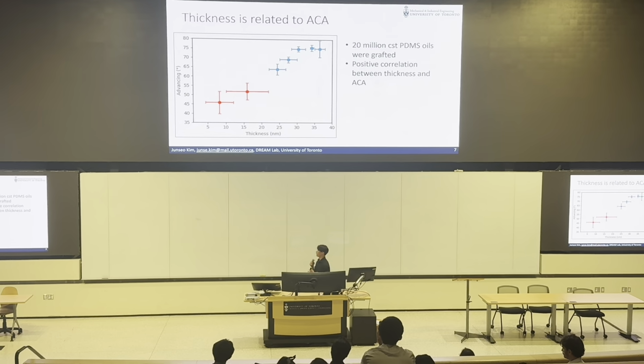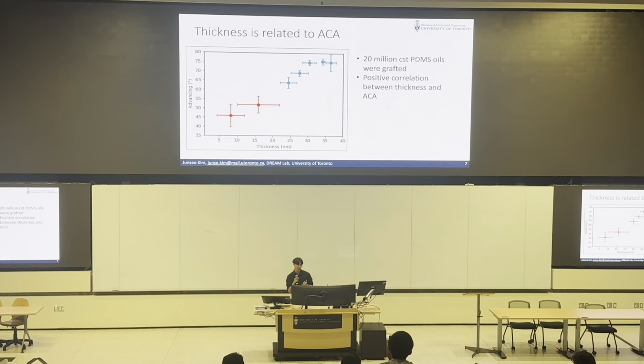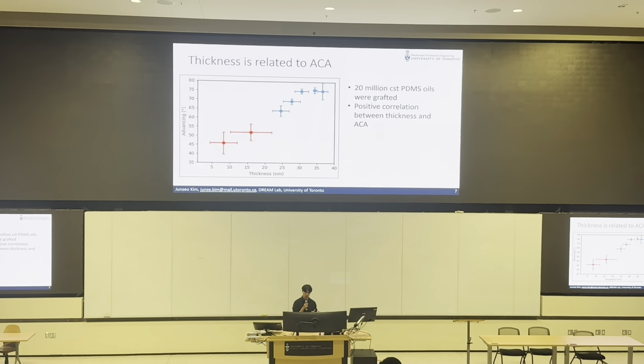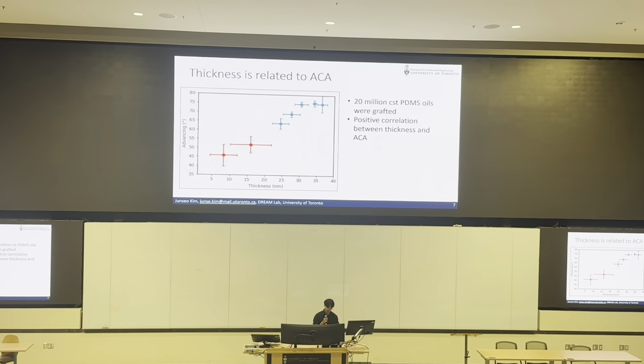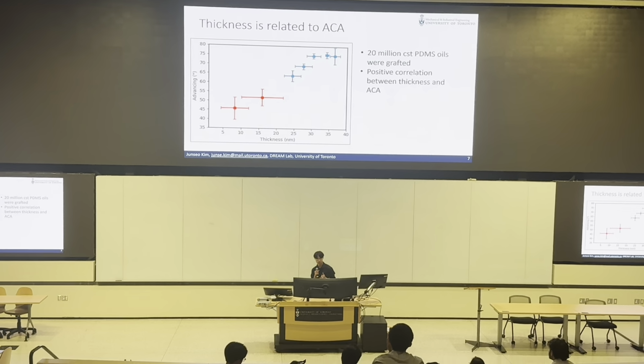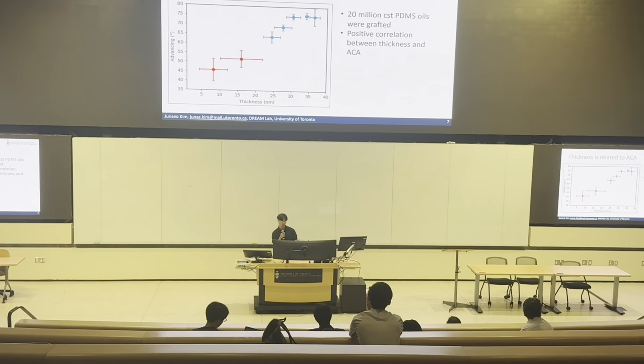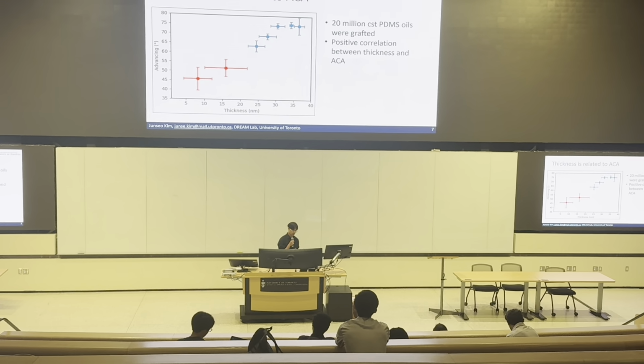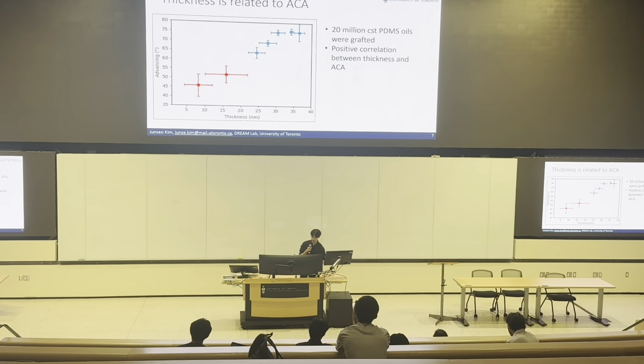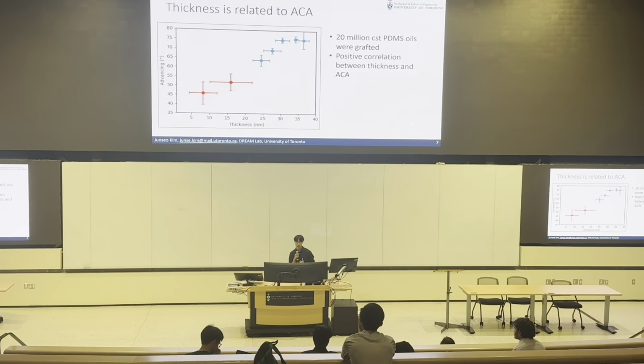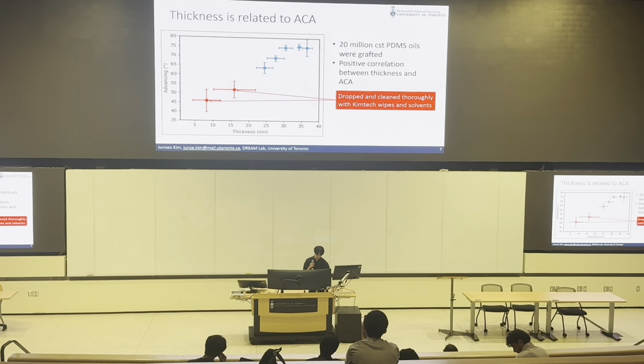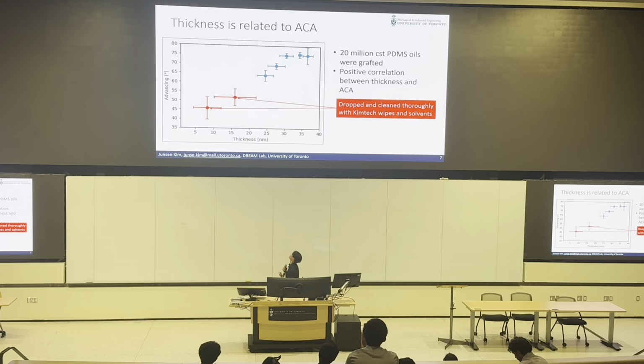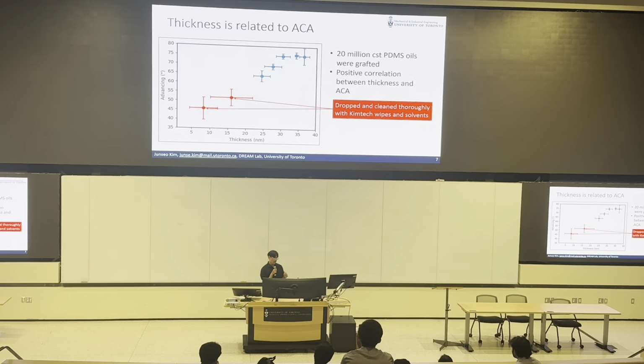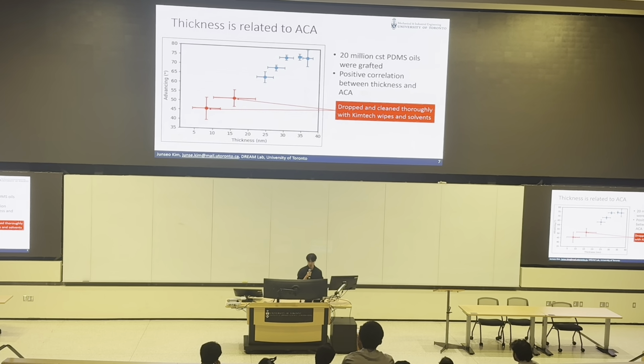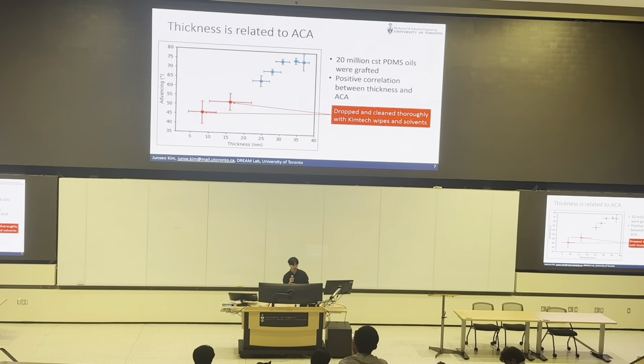Another thing that I found out was that thickness is related to advancing contact angle as well, not just the molecular weight. You can see from this plot that there's a positive correlation between the thickness of the coating that's grafted as well as the advancing contact angle. This is for 20 million centistokes PDMS again, and you can see that positive correlation. However, you can see the data points highlighted in red, and those are samples that I accidentally dropped in the lab and they were contaminated.